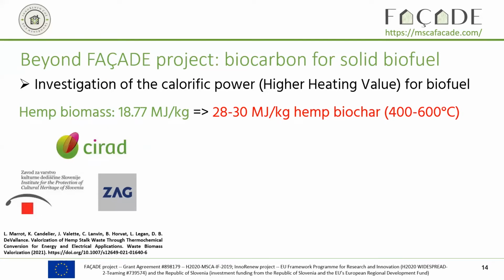Here I will present some work that was done in collaboration with CIRAD in France, with the Institute for the Protection of Cultural Heritage in Slovenia, and also the ZAG Institute in Slovenia. We looked first at the calorific power through the higher heating value of the biochar for solid biofuel application. When you look at the higher heating value of the hemp biomass, you get a result around 18-19 megajoules per kilo. And then when you get biochar from this biomass, you can increase the calorific power of the material.